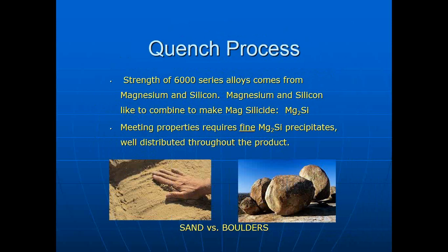And the best illustration I have of this is sand versus boulders. What we want is a profile that is full of mag silicide sand but doesn't have any mag silicide boulders in it. You could compare this to cement. Portland cement, like raw aluminum, is not particularly useful. You can sort of almost grout with it, but it's not particularly useful. You put aggregate in it to make it stronger. But if you were pouring a 4-inch driveway and you threw a bunch of 3 to 4 inch diameter stones in the mix, you would have a real problem. You would have holes, you would have cracks, all kinds of problems. You need aggregate, but it has to be a lot finer. The same here. We're looking for very fine particles evenly distributed throughout the product.